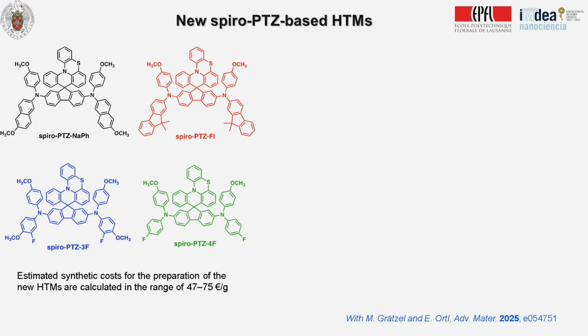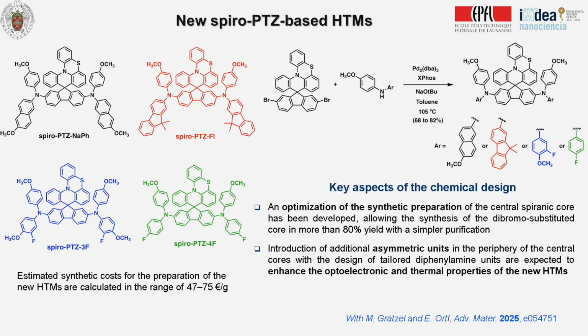And we synthesized in our lab these materials, which have the same central core, but only with the phenothiazine, because it turned out to be the most efficient one. So we removed the oxygen and we use only sulfur again. And this is interesting because look, this is the expected cost for 1 gram. And what is remarkable here is that now the molecules are asymmetrical, so they are not symmetric like the previous ones. This paper was carried out in collaboration with Michael Grätzel, because we sent the postdoc to his lab for carrying out some experimental studies. And also with Enrique Ortí, who is in the audience, and he is a theoretician, and he will give you a lecture, so I will pass this part of my presentation to him.